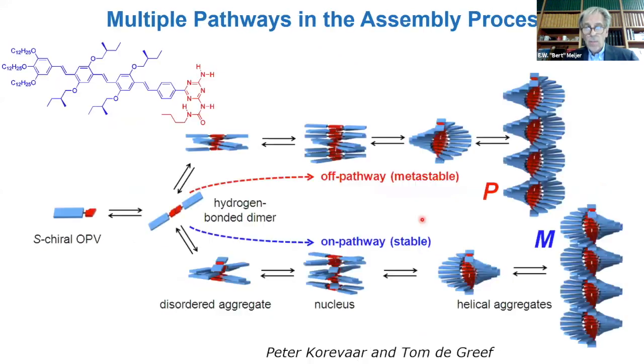But then it became more complicated because we came to the conclusion that if you have that nucleated state, like in crystallization of small molecules, you have multiple pathways. You have a kinetic off pathway, and you have a thermodynamic on pathway, a more stable aggregate. And it's beautifully shown on this molecule, done by Peter Korevaar and Tom de Greef. They go into helical structures. They prefer one helicity due to stereocenters in the molecule. However, it starts to form the P helix, and the P helix dissociates again to make a new nucleus on this way, and you end up with the M helical structure.